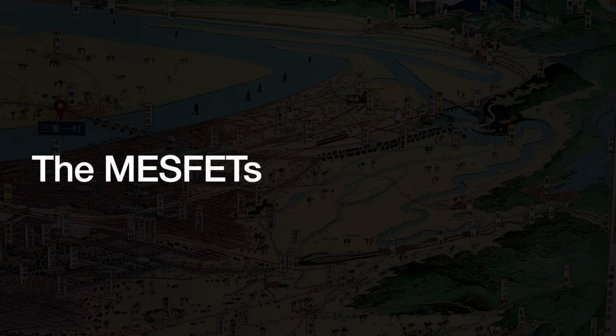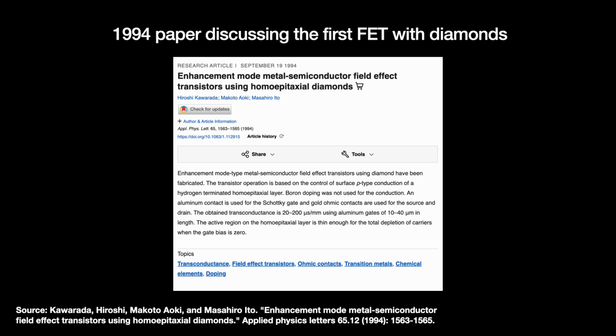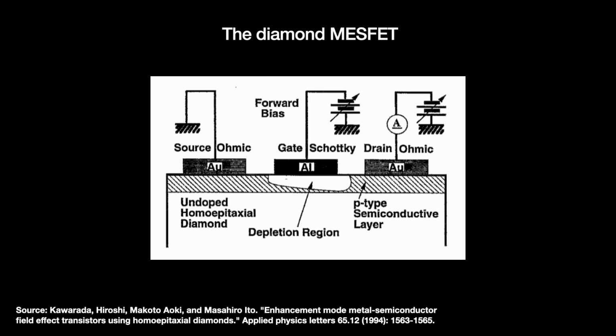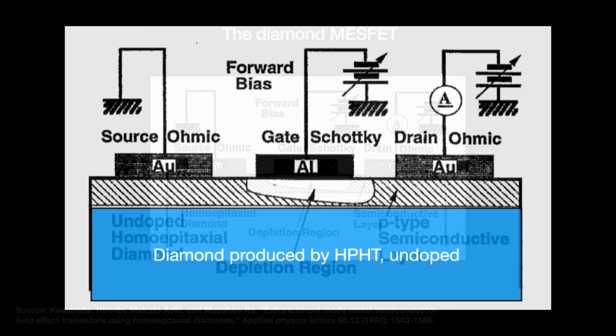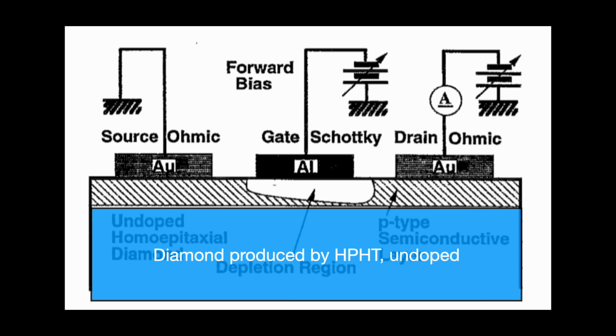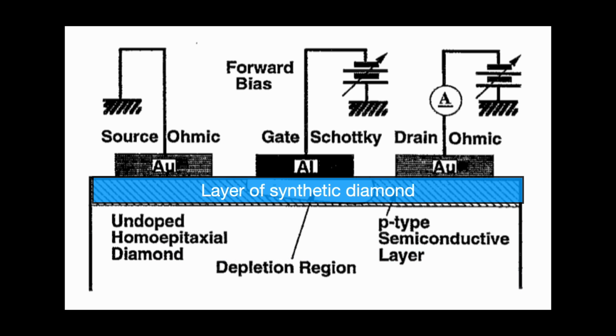They demonstrated a MESFET, a metal semiconductor field effect transistor, meaning a type of layered transistor with the source, drain, and gate all made from a metal. We start with the substrate, made from undoped HPHT single crystal diamond. A layer of diamond was grown on top of that with MPCVD. Hydrogen termination via microwave-enabled hydrogen plasma is then used to make that layer p-type conductive, moving electron holes.